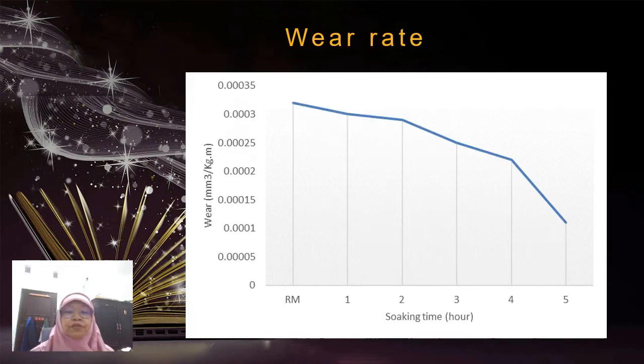This figure shows that the wear rate of the FeAl-MnMo alloy is 0.00032 mm3 per kilogram meter. This wear rate is quite low because of the presence of elemental aluminum, which forms carbide compounds, and FeAl, alpha FeAl intermetallic compounds, which are hard.